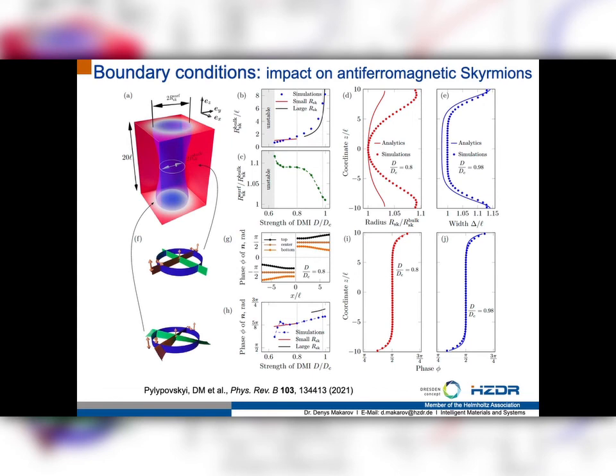So this is a slab of G-type chiral antiferromagnet where you can support the formation or stabilization of an antiferromagnetic Skyrmion. And again, the same story applies. As soon as you are far away from the top and bottom surfaces, you will have bulk-like properties of, for example, a Bloch Skyrmion. But as soon as you approach the surface, you will have, for example, broadening of the Skyrmion, the radius will change, the phase of the Skyrmion will change, it will become a mixed Bloch-Néel Skyrmion and will be substantially modified. Again, the characteristic length scale where the modification happens is in the range of a couple of exchange lengths, like 5 to 10 exchange lengths. This is also something like a design rule for the experimental community, which will need to take care that the thickness of the sample is sufficient in order to have at least bulk-like behavior of these antiferromagnetic Skyrmions. Otherwise, what you see from theory and from experiment will be pretty much different.